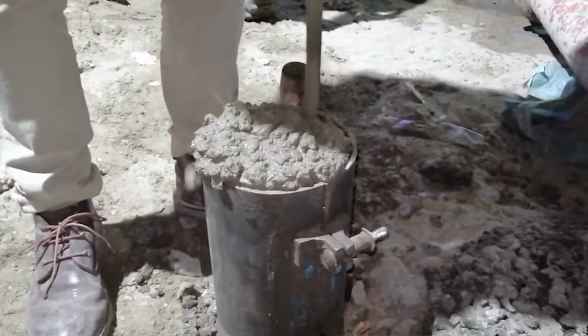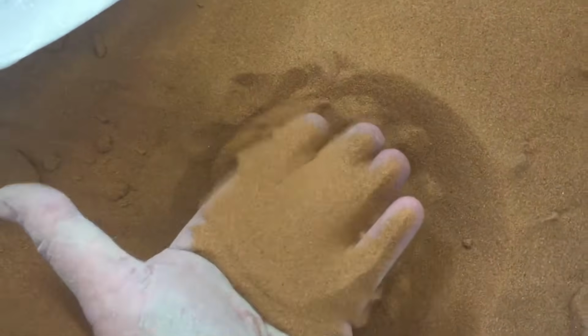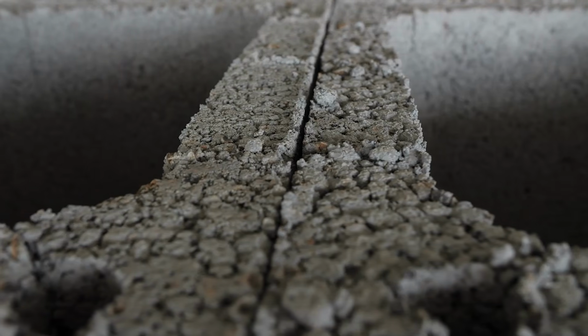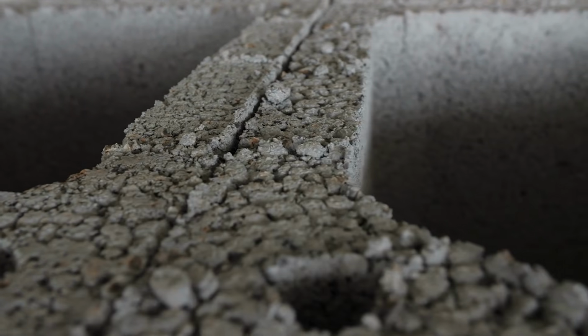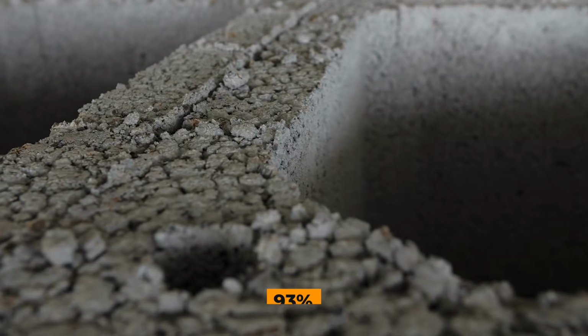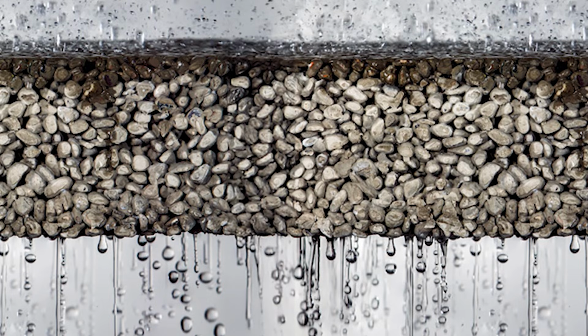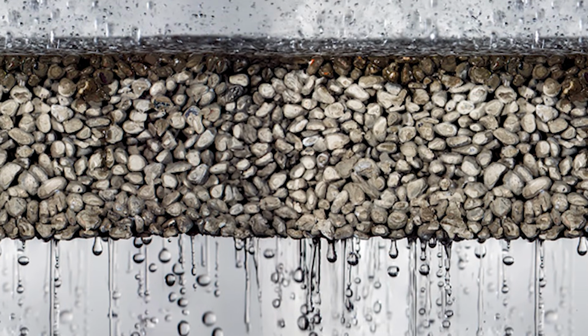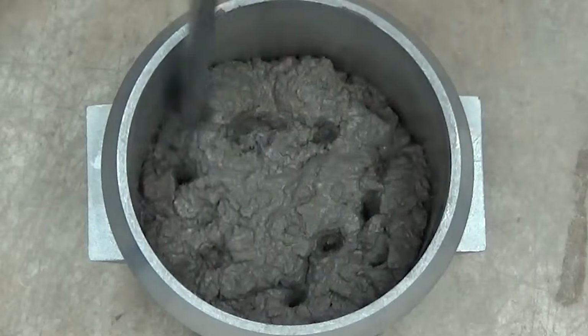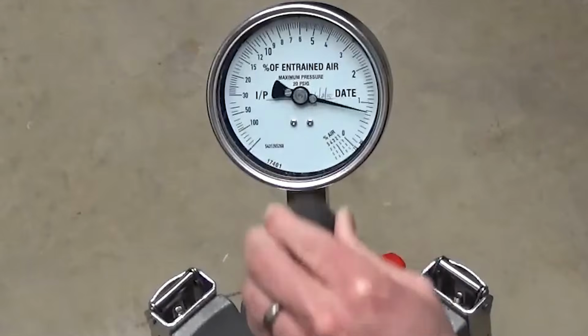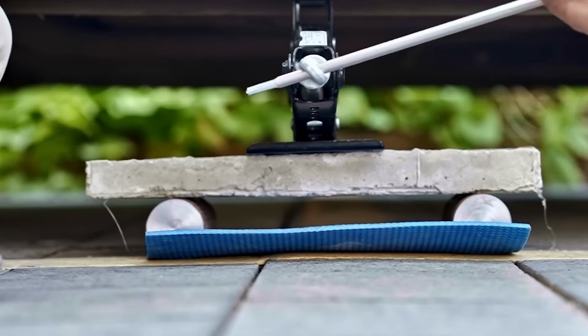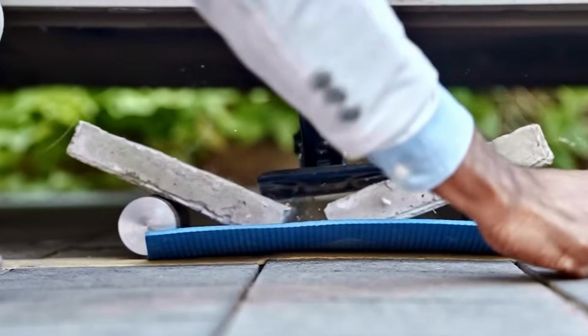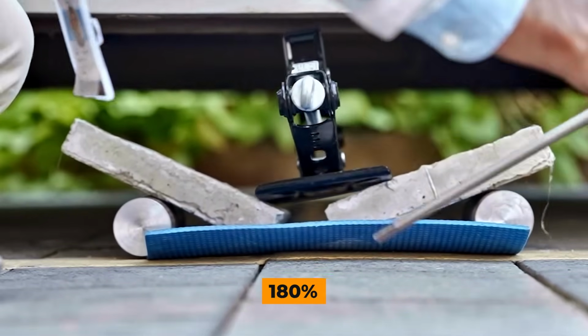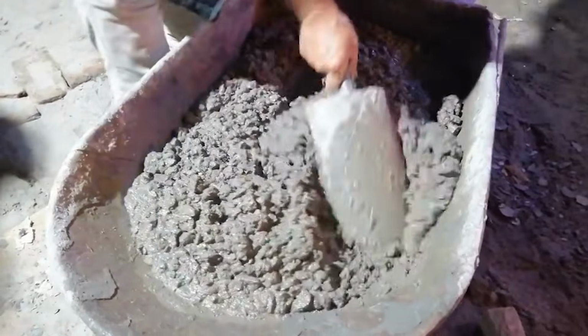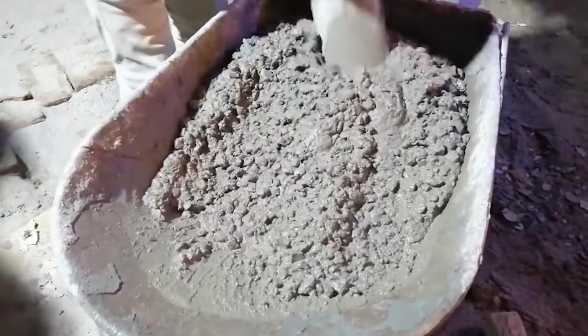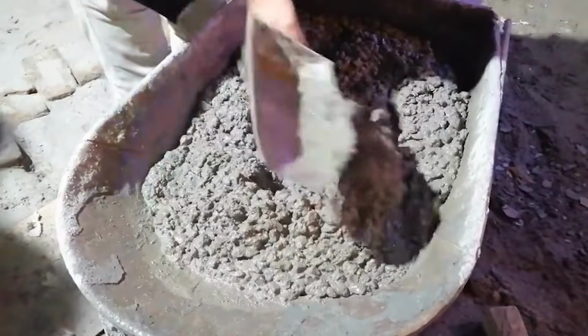The measured numbers back this up. In studies on desert sand concrete, a notoriously weak material, compression casting increased compressive strength by as much as 93% and cut porosity and water absorption by well over a third. In other layered compression studies, strength gains around 100% were recorded. One compaction study pushed the strength improvement even higher, past 180%. The exact figure shifts depending on the mix and the pressure applied, but the direction is always the same, and